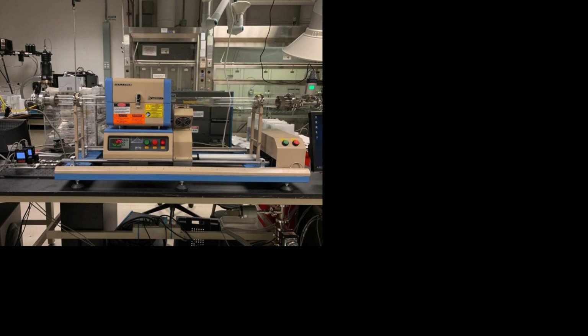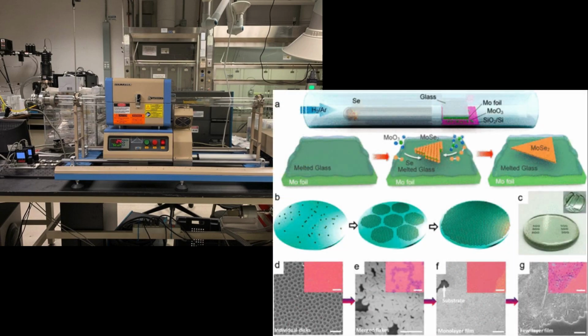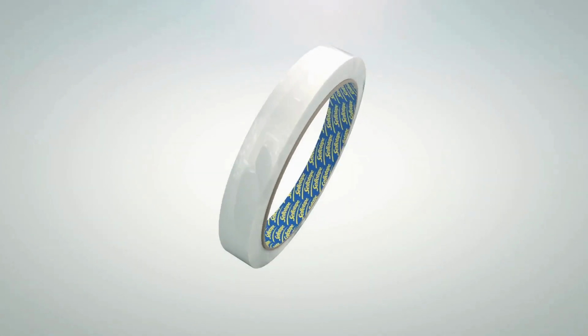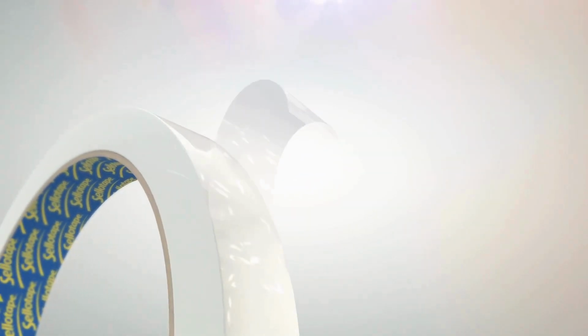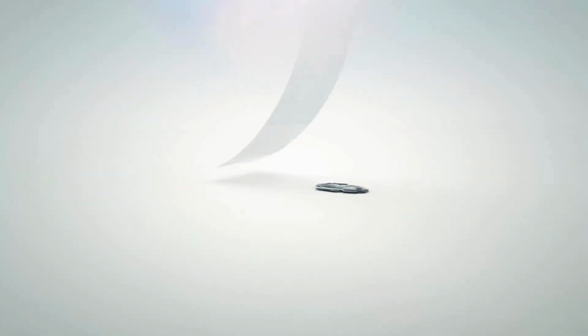The following video presents the fabrication process of 2D materials through mechanical exfoliation along with the adjustable parameters. Other methods have been developed to create large monolayered materials. However, as is the case with chemical vapor deposition, the 2D material fabricated is polycrystalline, with many grain boundaries influencing the material's quantum properties. Therefore, this project focused on the cost-effective method of mechanical exfoliation, capable of creating monocrystalline flakes within the specifications of our sponsor's request.